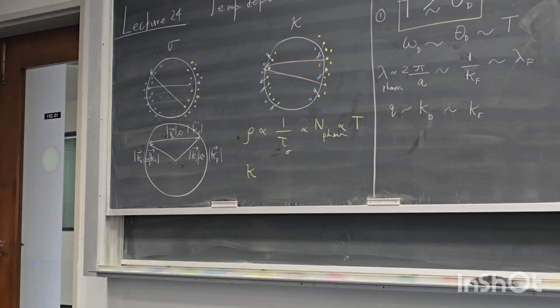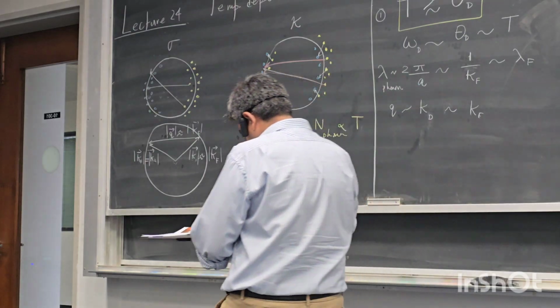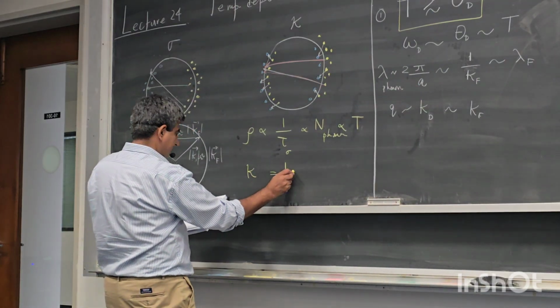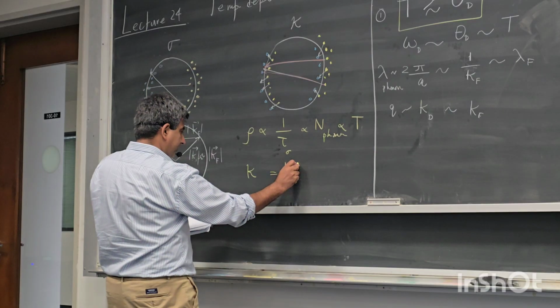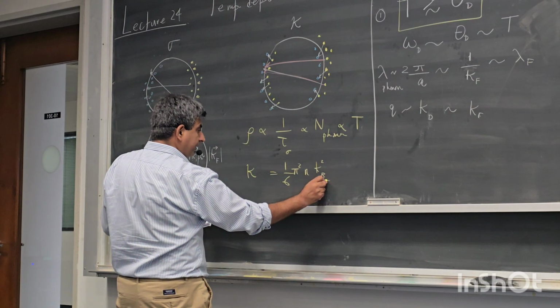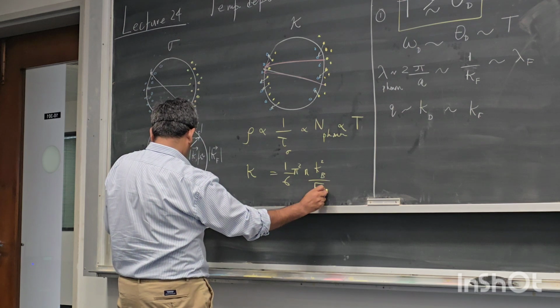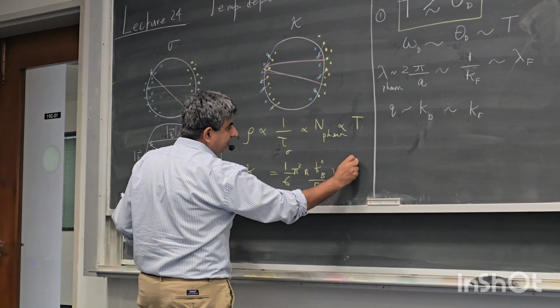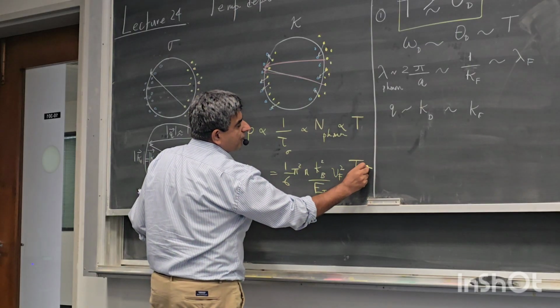It's basically the prediction is 1/3 pi squared n kB squared EF vF squared, all of these are constants, temperature into tau kappa.